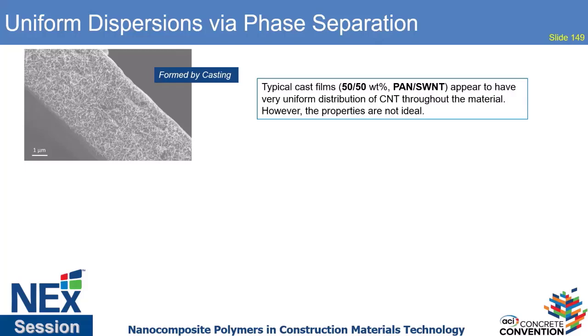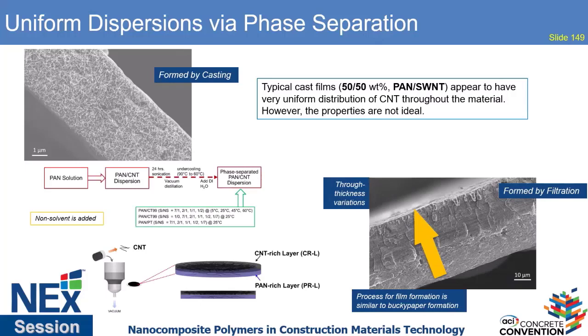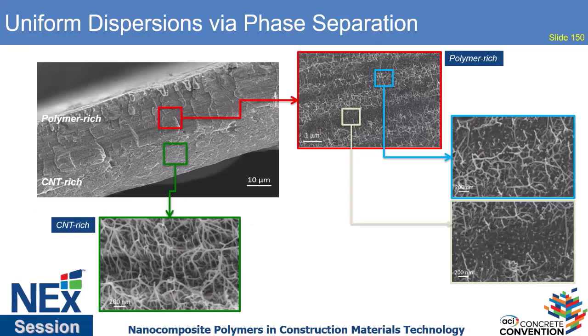However, when we incorporate a phase separation process where we treat the nanotubes with a non-solvent and solvent system, what happens is in that same film we see a two-layer structure. We see something where all of the nanotubes look to have fallen out of the film. However, when we look closely at this material, we can see that within these two layers we have two different sets of nanotubes, essentially because the nanotube sample is heterogeneous. You have bigger and smaller bundles depending on how you mechanically disperse these materials. The polymer is able to capture some of it, and some of it is actually rejected by the polymer.